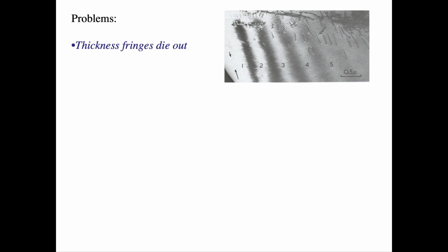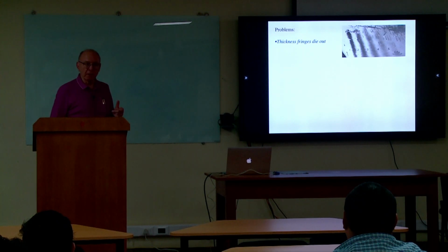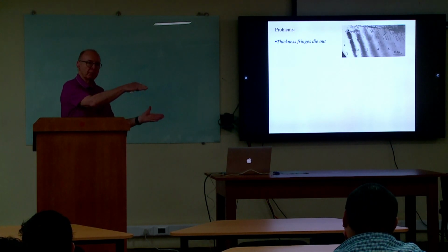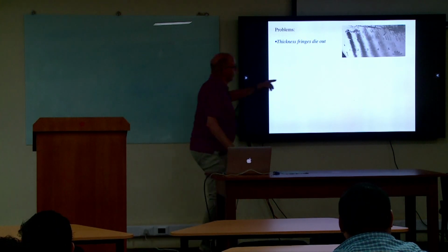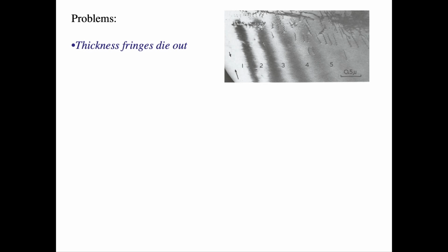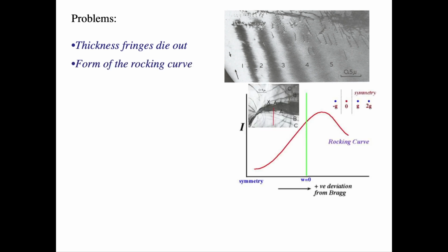So that could mean one of two things, right? The first thing it could mean is we've got a variation in thickness that becomes constant, and therefore we don't really get any fringes. Right, so we're getting thicker and thicker and thicker, and then we're not getting thicker after this. So that means if you're a defender of the geometrical theory, you're going to say, haha, that's what we have. But actually you don't, because when you make a thin foil, it keeps on getting thicker. So we're losing information here that we can't explain by the geometrical thing.